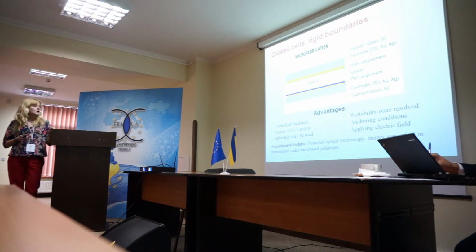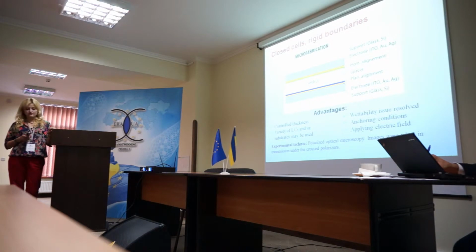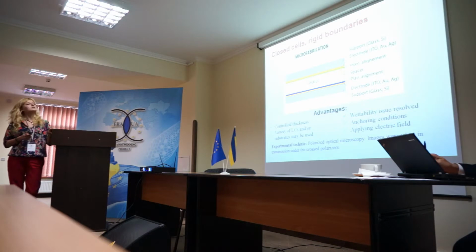And there are some other advantages: the wettability issue was resolved, so that we were able to use different liquid crystals and different substrates, varying anchoring conditions, and in addition, we were also able to apply an electric field, which, as I have said, we applied perpendicular to the substrates. Further, we used mostly polarized optical microscopy, and the images that I will show you were taken under crossed polarizers.